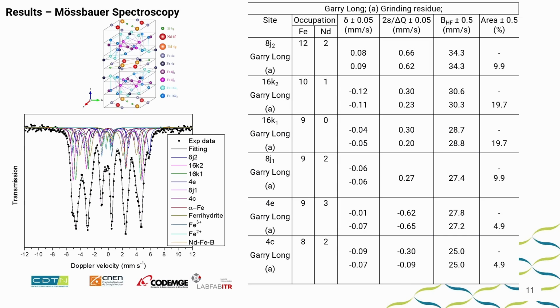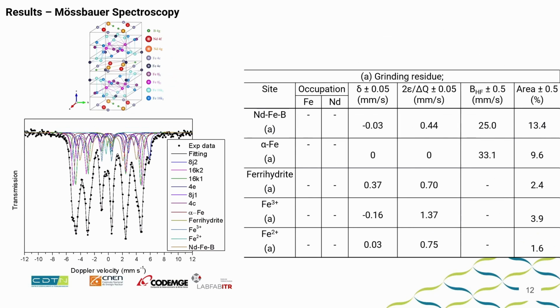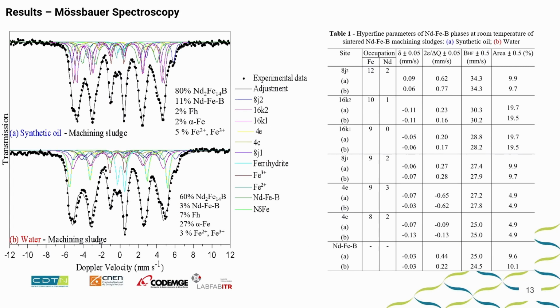So this is the site of the non-equivalent sites of iron, and the other phase with the distorted crystal structure, and we agree on some values of this hyperfine magnetic field. I can say in the average, like many Chinese articles and so on, it's almost 27 Tesla. And this is the other parameters with the distortion of the structure of the neodymium iron boron. It's less magnetic hyperfine field, and this is with the oil synthetic fluid.